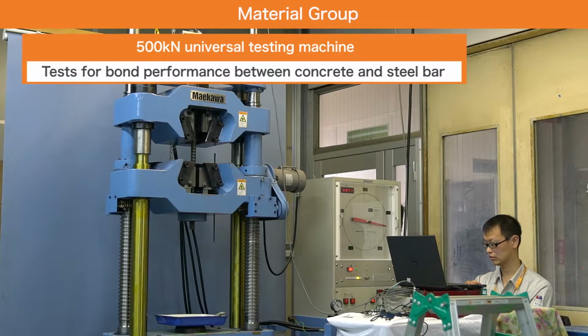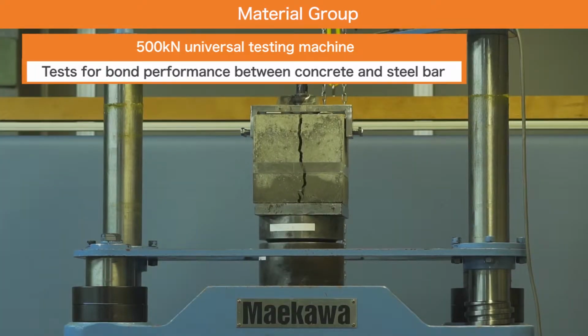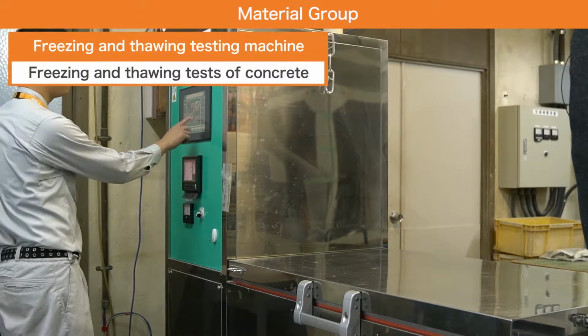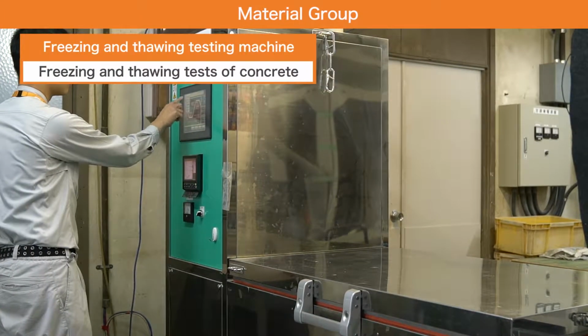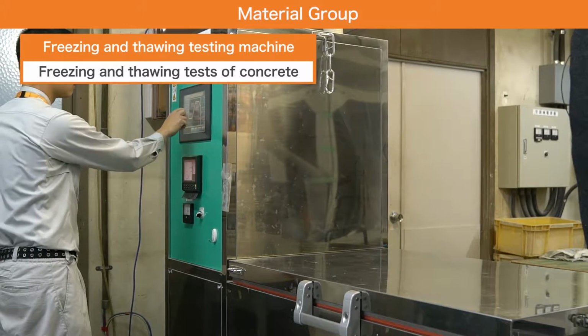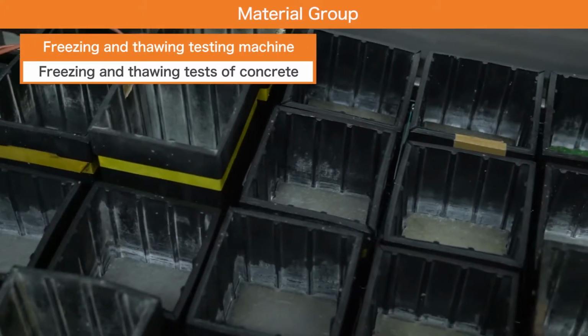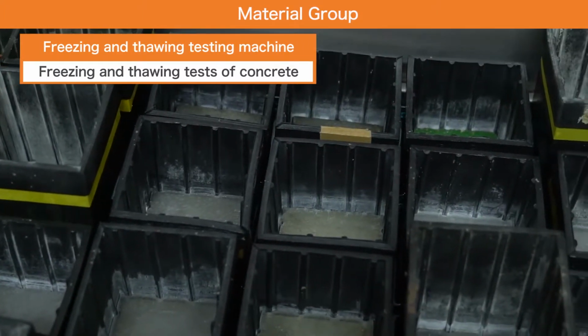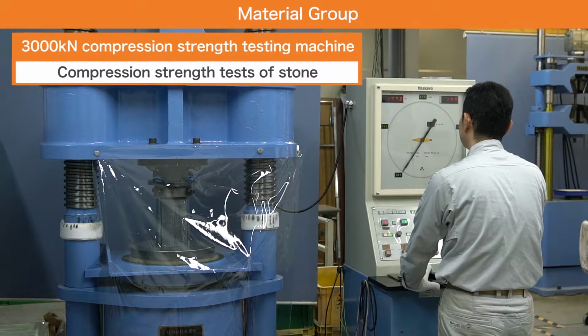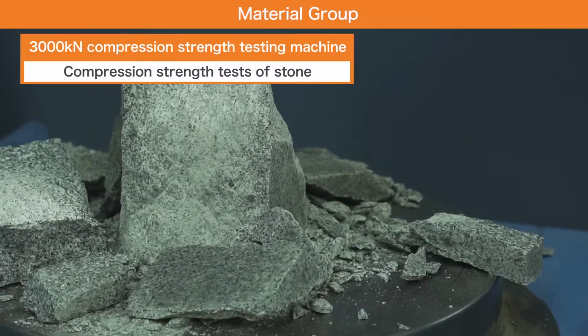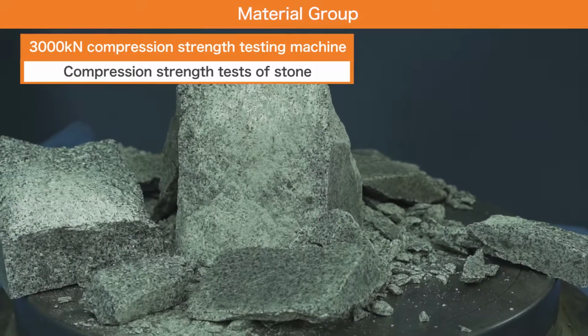The bond performance test between the concrete and reinforcing bar is a test to check bond performance by pulling out the reinforcing bars cast in the concrete. The freezing and thawing test is designed to repeatedly apply freezing and melting actions of water to concrete and examines deterioration conditions. The compression strength test of stones is a test to examine the compressive strength of stone used for finishing materials and rough quarry stone using a compression testing machine.